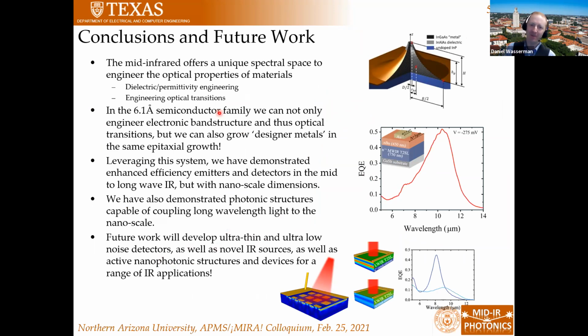So I'll just say that the mid-infrared offers a unique spectral space to engineer the optical properties of materials, but also to engineer device architectures and optical transitions. And we can do this all in the 6.1 family of semiconductors. And we've leveraged this system to demonstrate enhanced efficiency emitters and detectors in the mid to long wave IR, but with nanoscale dimensions that are essentially state of the art, right? And so we've shown that we can couple light, long wavelength light, down to the nanoscale. And as we move forward, we're looking to develop ultra thin, ultra small, sub-diffraction limited optoelectronic devices for the mid-IR with state-of-the-art performance compared to existing commercial devices.